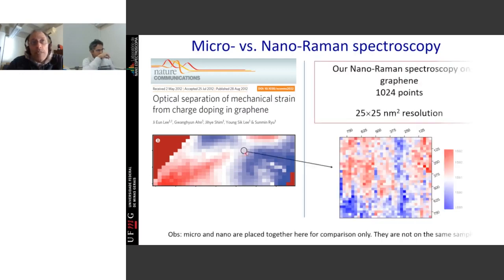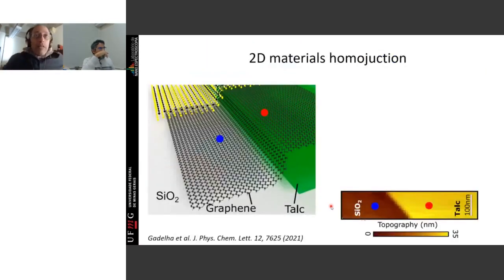And what we can do now is you take this 1 pixel and you do the scanning with a much higher resolution. So now this is 1 micron, the entire piece is 1 micron. And we show that inside this one spectrum from the Korean fellows, you also have strain and doping localized on a much smaller scale, in a nanoscale, as compared to the large scale that was characterized by the Koreans. Okay, and let's do some interesting device characterization and understanding with this.